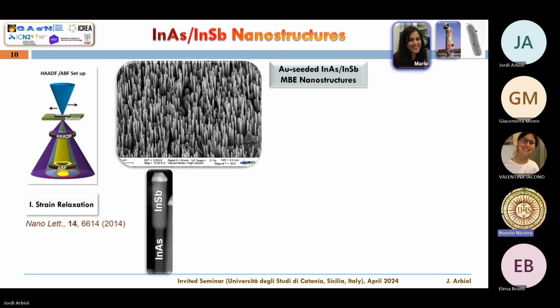When you think about quantum materials, you want one of these semiconductor materials that have maybe a small bandgap, but also a really high mobility. And when you think about a high mobility, you can think about indium arsenide, but the best material is maybe indium antimonide, or one of the best, for the mobility reasons. But it's really difficult to grow indium antimonide nanowires, at least by using this VLS technology. So what you need to do is growing first an indium arsenide nanowire, and then on top of that, you can grow the indium antimonide, okay?